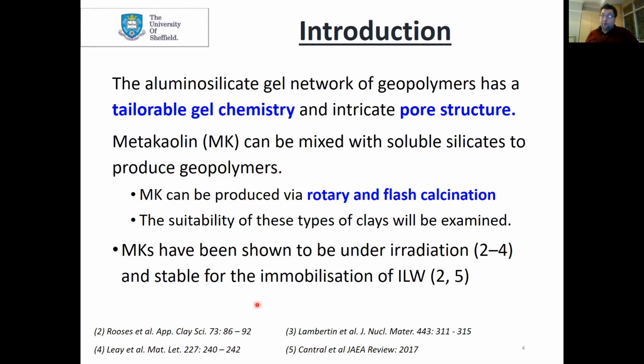So why would we pick something completely away from Portland cement? Well, these are completely different, and they go by a completely different mechanism. You react an aluminosilicate precursor with a highly alkaline soluble silicate solution, and when you react them together, you completely dissolve the metakaolin away, and then form a new gel network. By that, you can tailor it to the exact properties you want from that material.